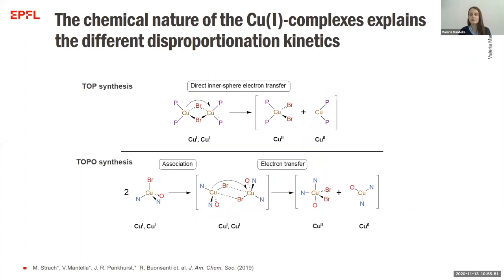So in order to explain these different disproportionation kinetics, what we did was to consider the chemical nature of these copper one complexes that we saw forming during the first stage. And so during the synthesis with TOP, the disproportionation is more favored considering the proximity of the two copper one centers in the bimetallic complex. Instead, during the synthesis with TOPO, the disproportionation is slower because the first two equivalents of the monometallic complex should approach one another and then associate to favor the electron transfer.